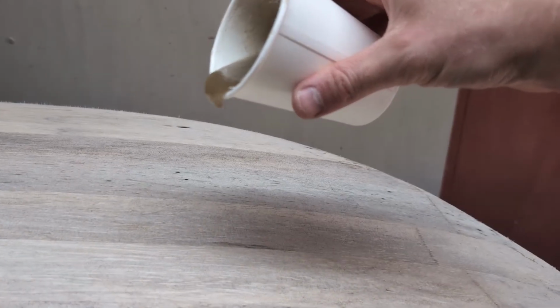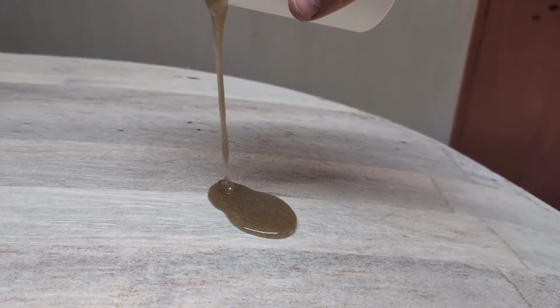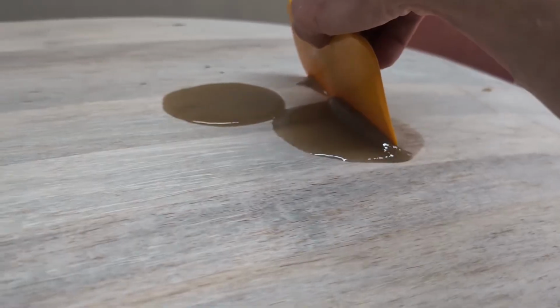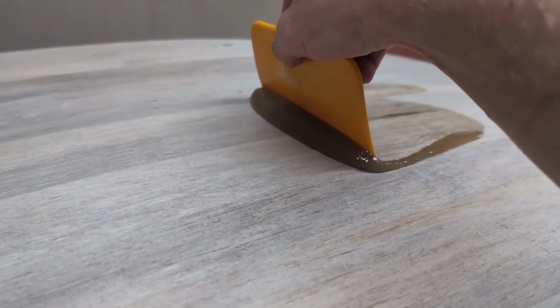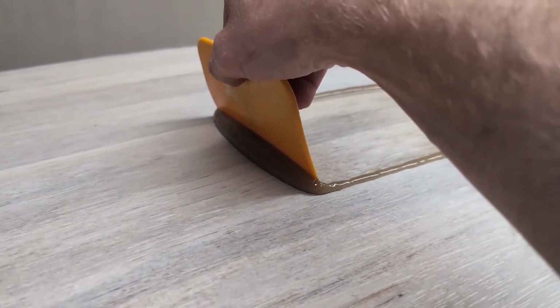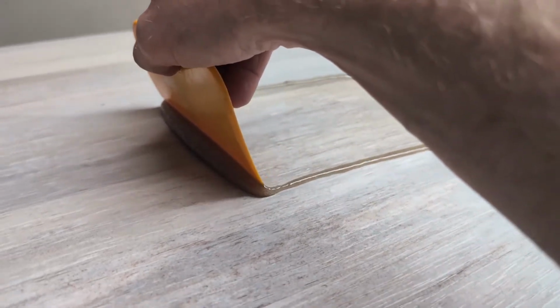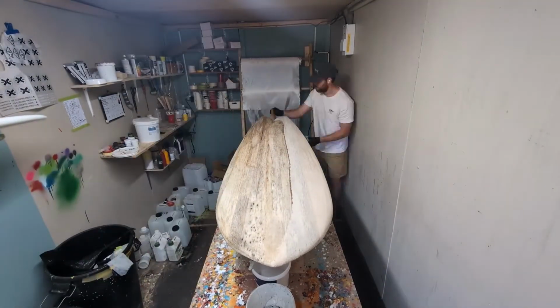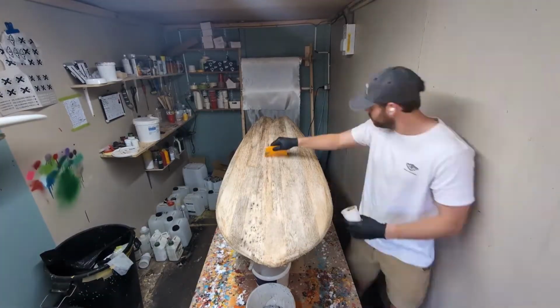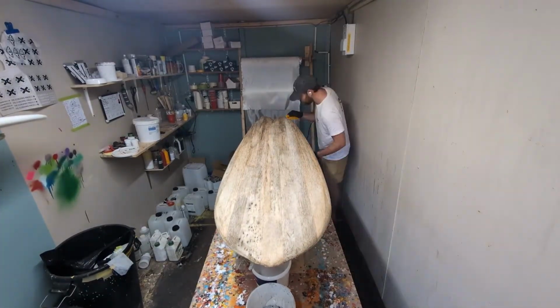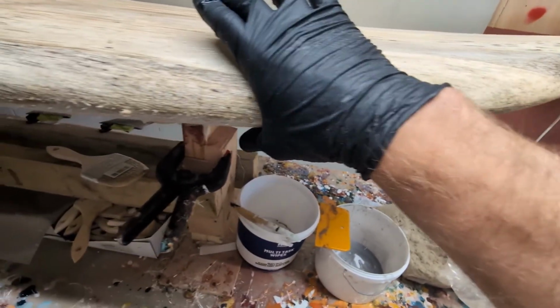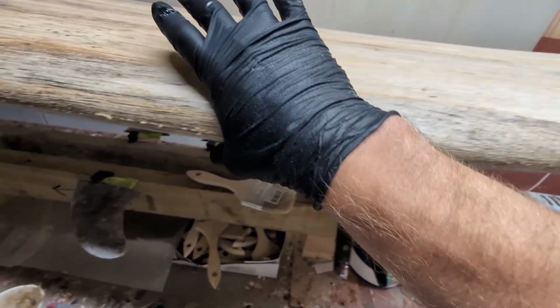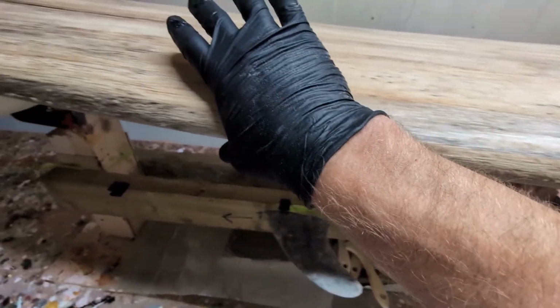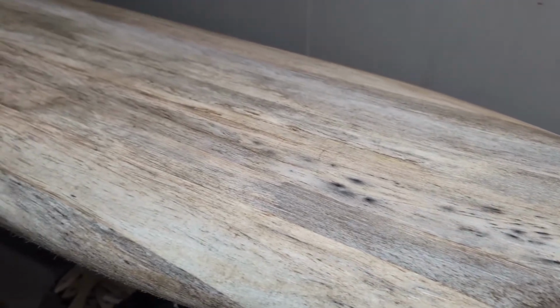If we were to just laminate straight away, we would likely have big problems with off-gassing, depending on the changing air temperature. This wood is light, meaning it's got lots of air in it. If the air temperature was rising, that would cause any laminate on the surface to trap air bubbles between the wood and the laminate. To seal it, I'm just using bio-epoxy resin mixed with milled hemp fibers.